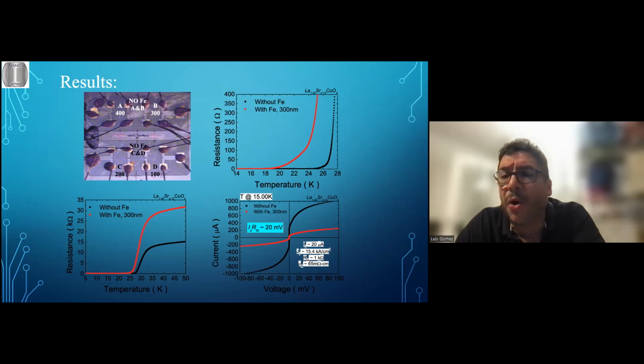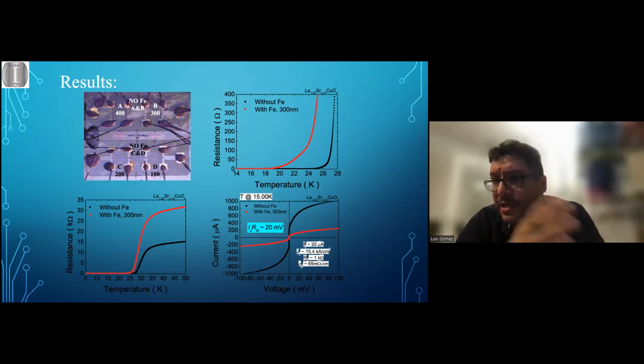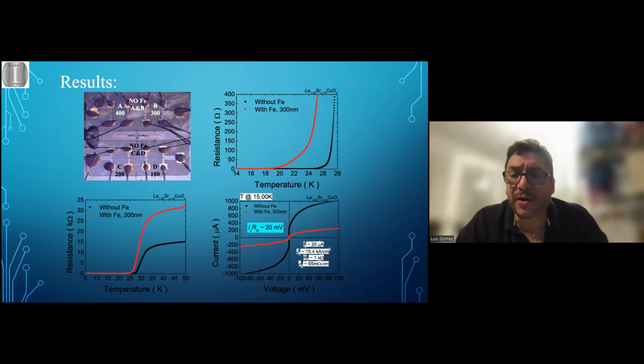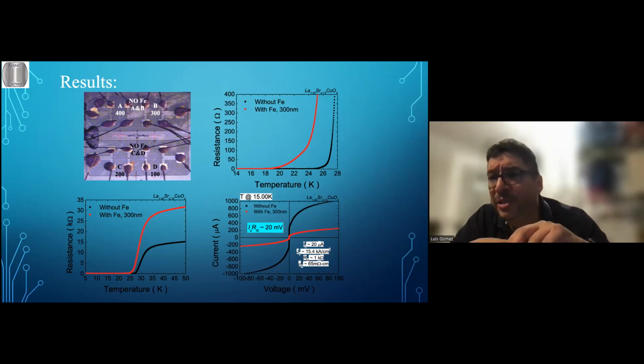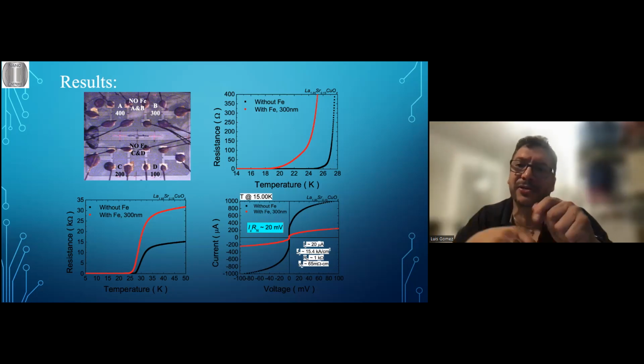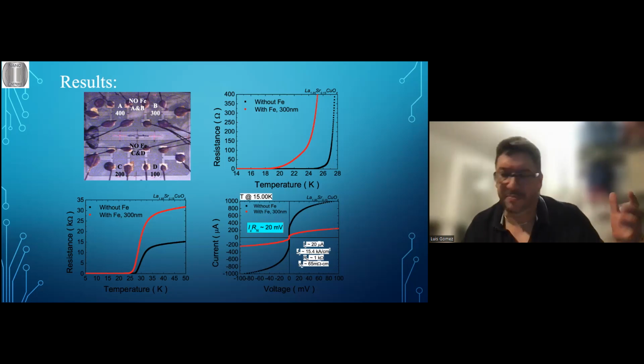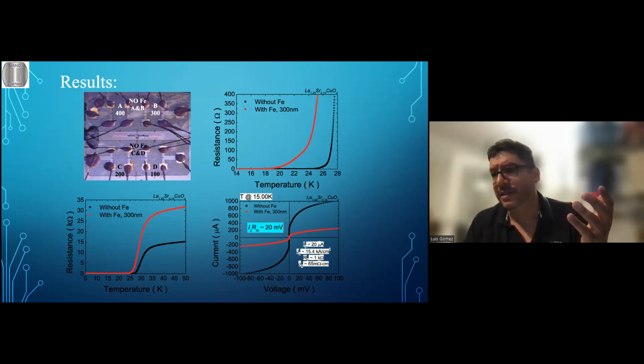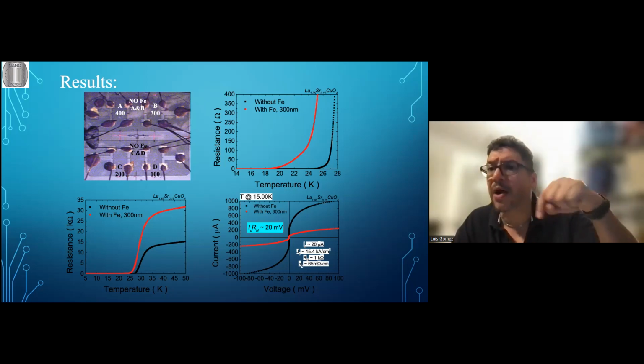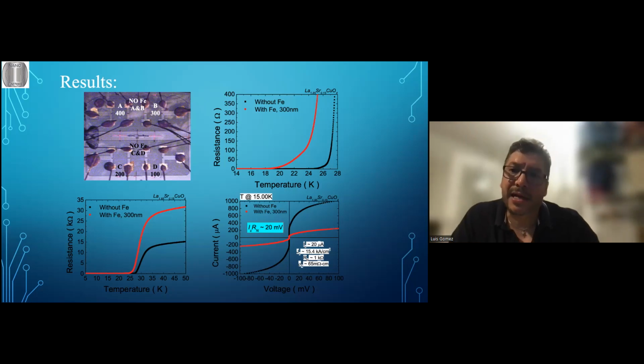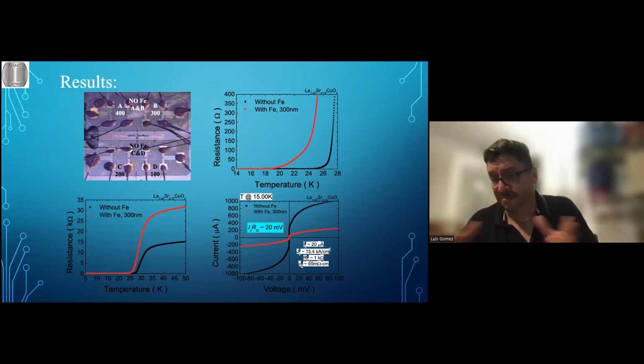Well, we might have the noise. There is a controversy about the origin of such a high resistance in this system. There is something I didn't mention so far: what we believe is that inside these systems there is something called a vortex of current. I don't want to go into the details of all the different descriptions of this type of superconductors. They're called type 2 superconductors, so the lines of magnetic field can go across the system everywhere. There will be loops of current going around each line of magnetic field. This is called a vortex. If you try to push current through this system, those vortices will move.